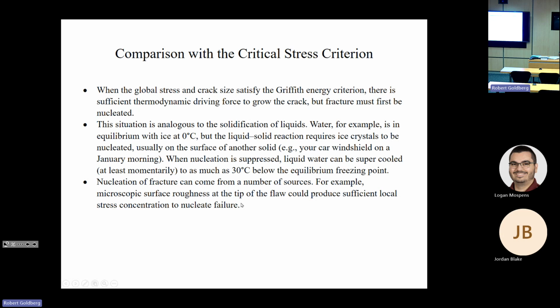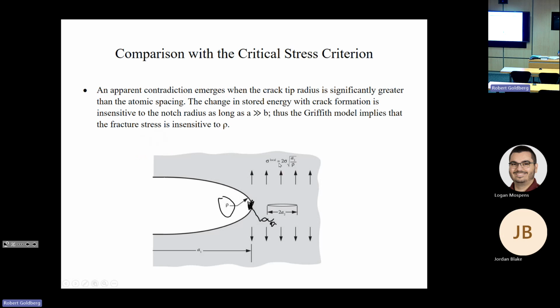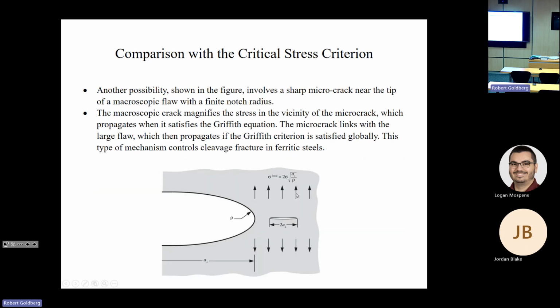start the failure process. Or another thing which can trigger the failure, which I don't remember if I did repeat the figure. Or another situation is where you have a big crack, but you have a sharp microcrack near the tip of the flaw. So this flaw has a finite notch radius, but you have a very small sharp crack right at the tip of this crack. So what you have is this macroscopic crack with the radius of curvature as shown in this equation here.